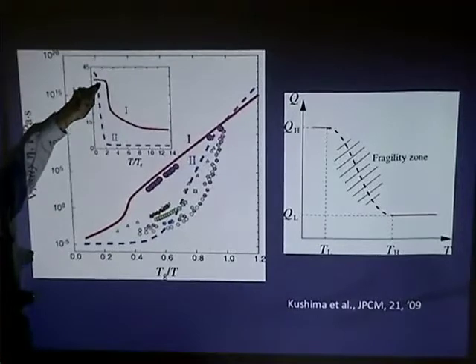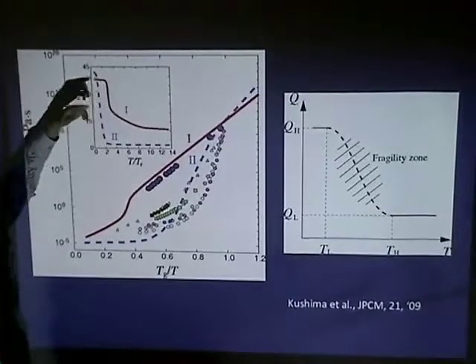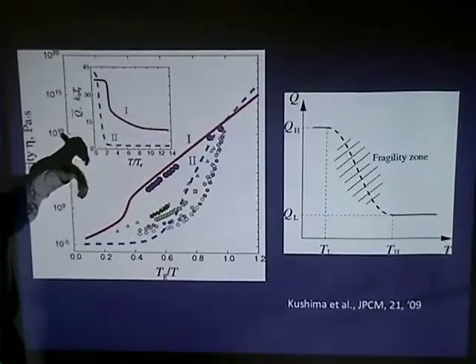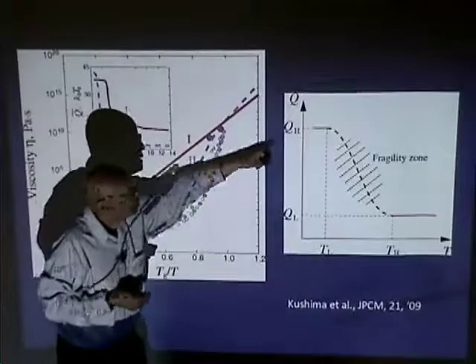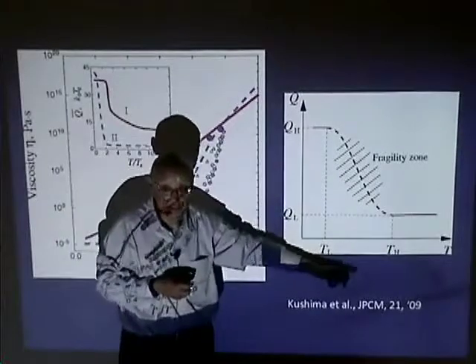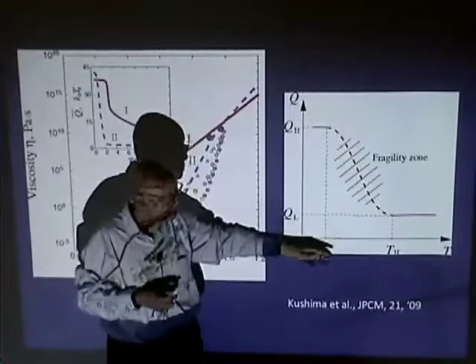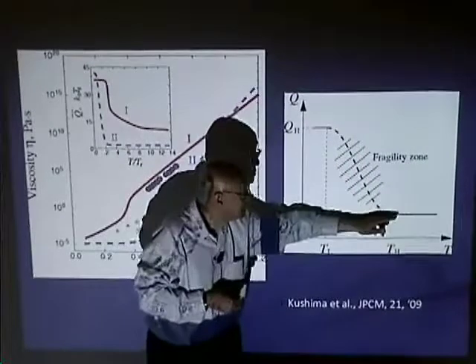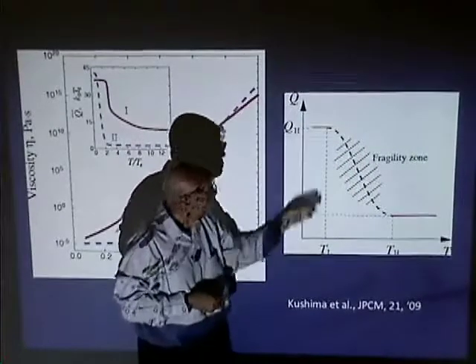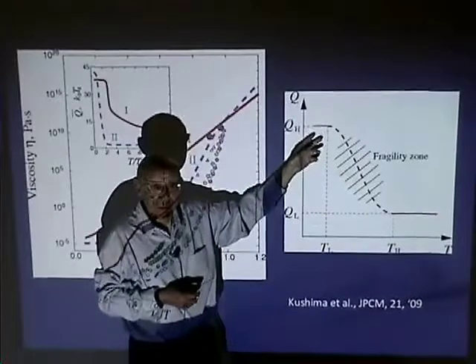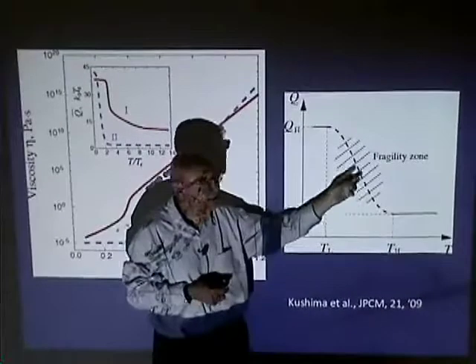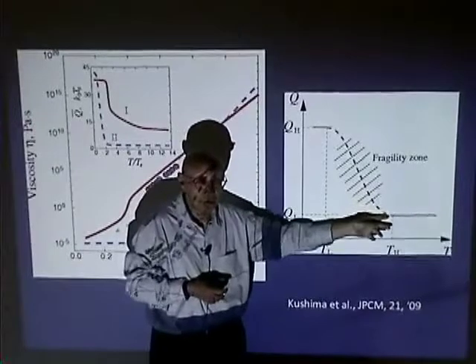At this point, a light bulb went on and said, okay, if you want a two-state model, here's a two-state model. Imagine you have an activation barrier as a function of temperature. It's a two-state model, all right? At high temperature, the activation barrier is low, and at low temperature, the activation barrier is high. And fragility is nothing more than that intermediate region where you go from low to high.